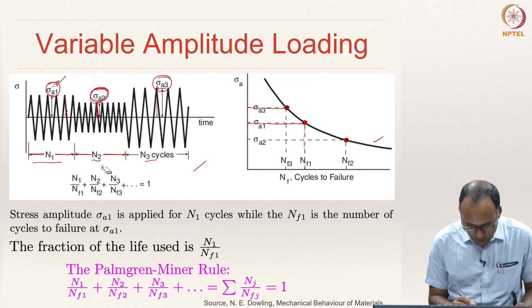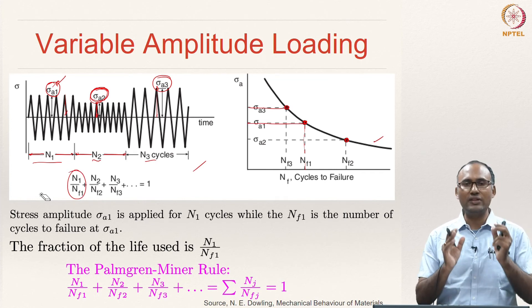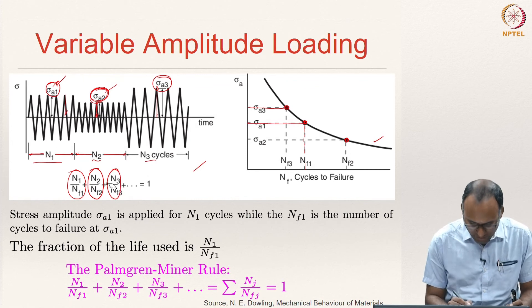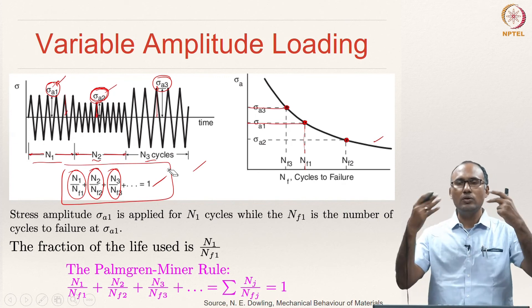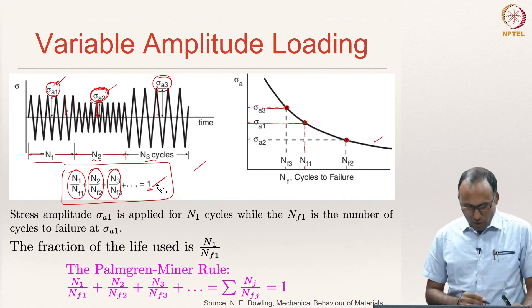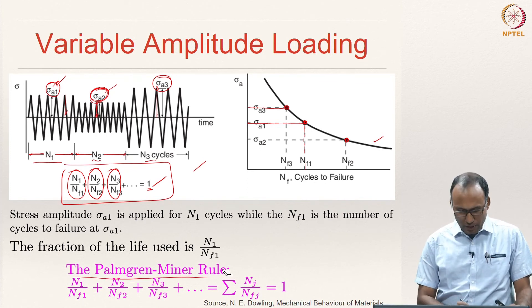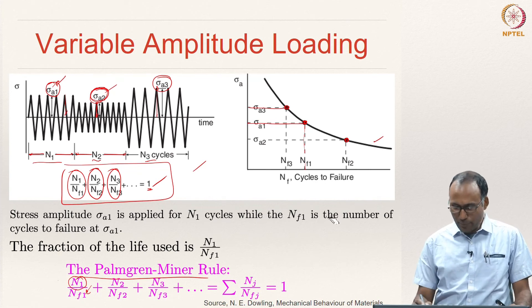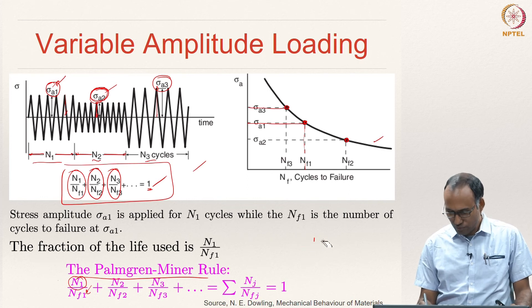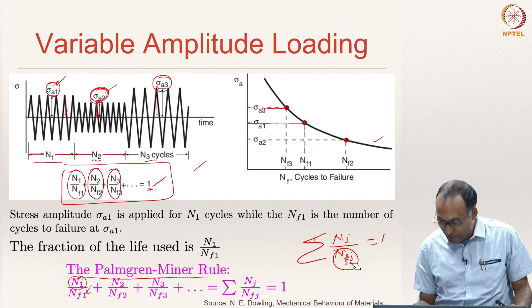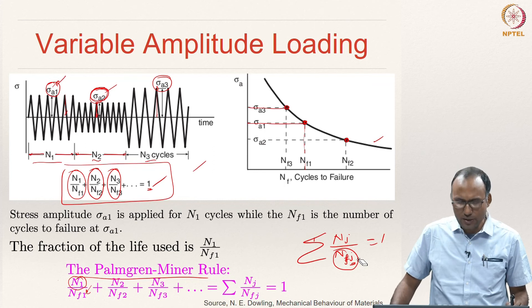So we can write: n1/nf1 as the fraction of life consumed by stress amplitude sigma a1, n2/nf2 by sigma a2, n3/nf3 and so on — all of them summed should equal 1, because the total life must be conserved. This law is called the Palmgren-Miner rule: if you have different stress amplitudes and the number of cycles used for a particular stress amplitude is nj while the failure cycles correspond to nfj, then you can write sum of nj/nfj = 1, where the denominator is the number of cycles to failure at that particular stress amplitude. This is how one can deal with variable amplitude loading.